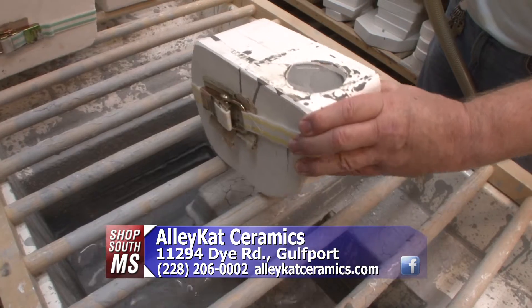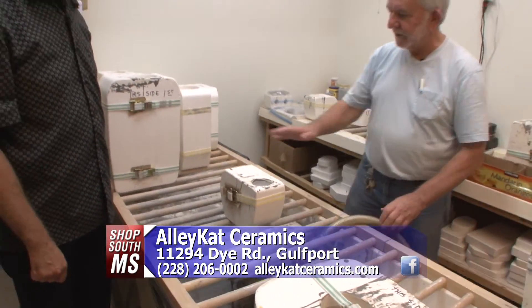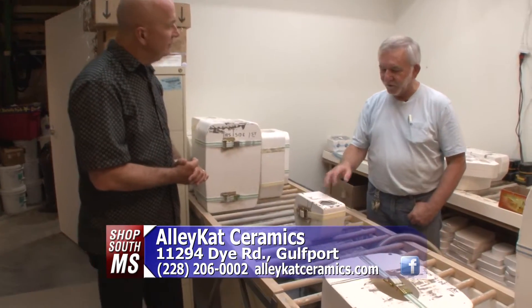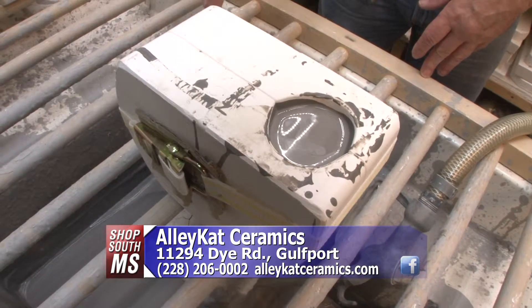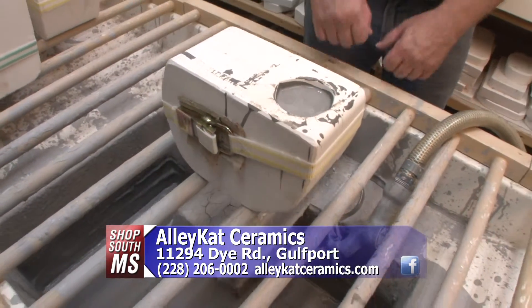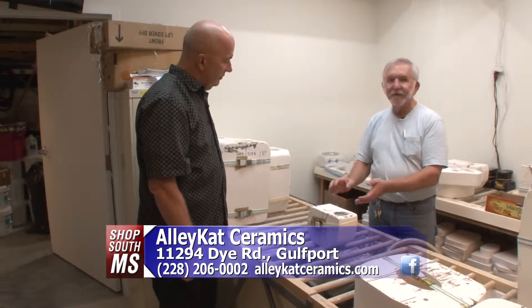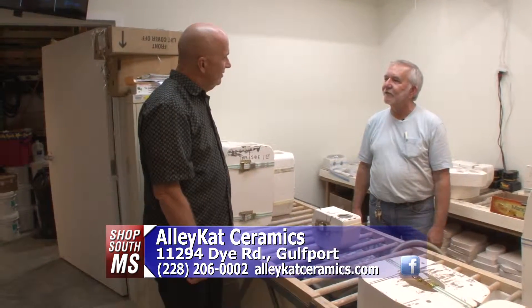Alright, what did you just do? This is a plaster mold that we use for creating our ceramic products. This is a liquid clay — we pump the liquid clay into the mold. Over time, the water will be absorbed from this slip and you'll build up a wall thickness. It'll get thick enough to the point where it's self-supporting. You'll empty the excess out, leaving you a hollow shell, which gives you your final product. You'll let it set for a while, open the mold, set it over on the shelf and let it completely dry before we bring it out to sell for the customers.